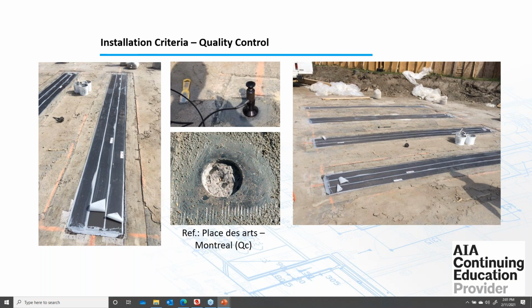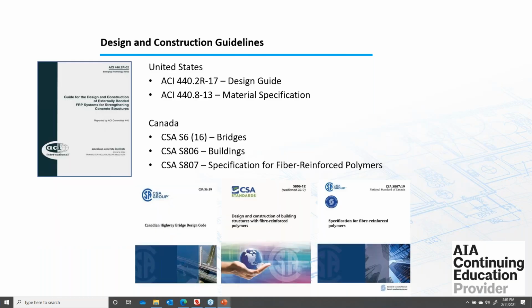Failure always occurred in concrete, and results were between 2.8 MPa and 4 MPa, which is about 580 psi, which is way above the minimum required of 200 psi or 1.4 MPa. That's it for me. Thank you for your attention. I will leave it to Brian to conclude our presentation.